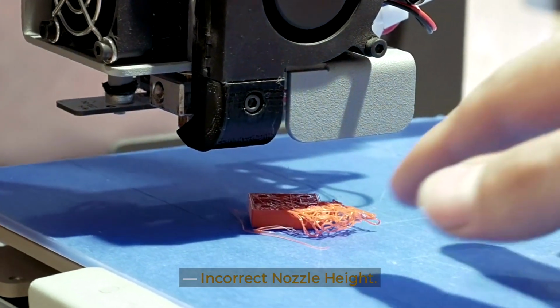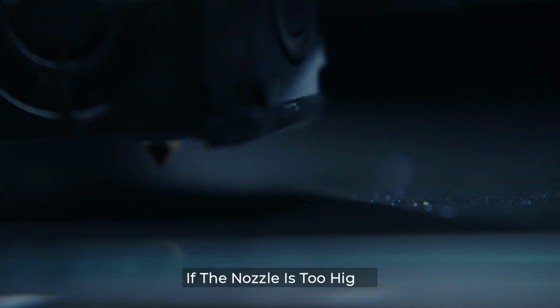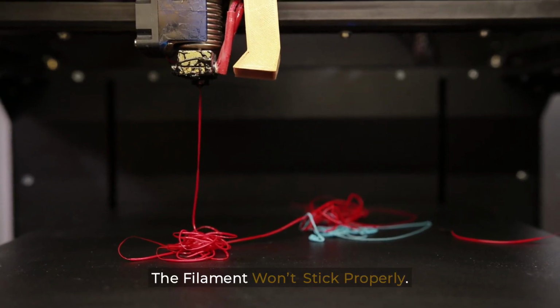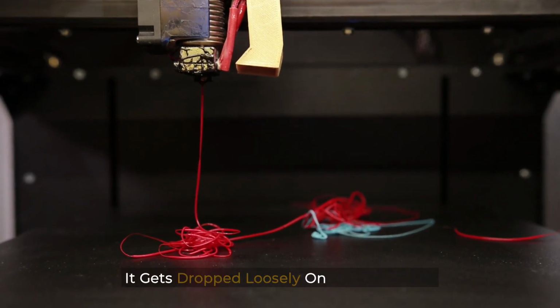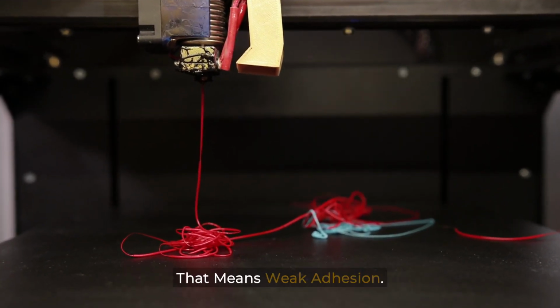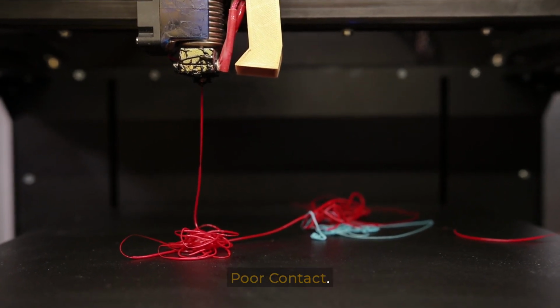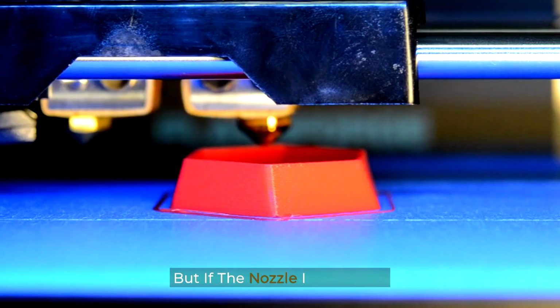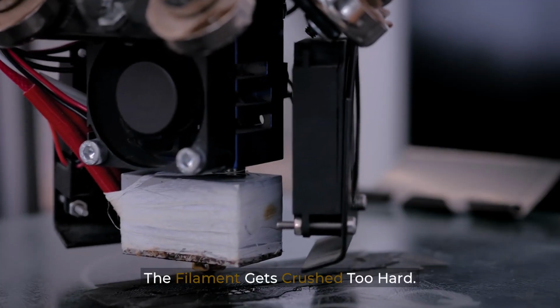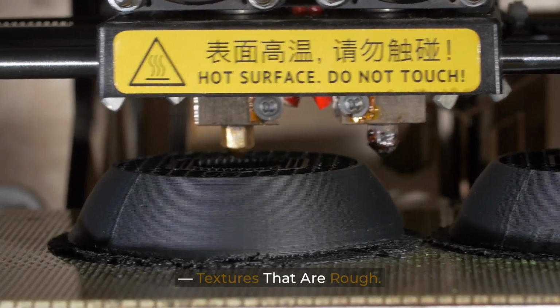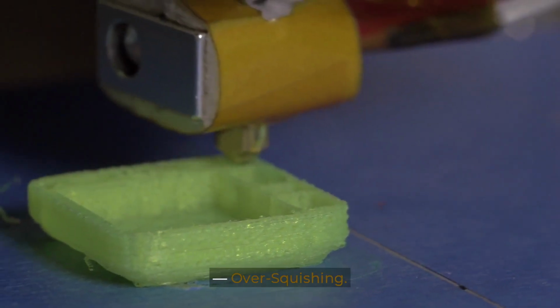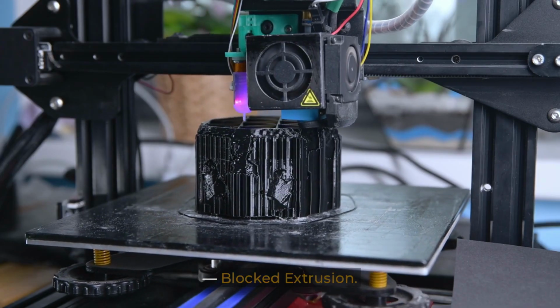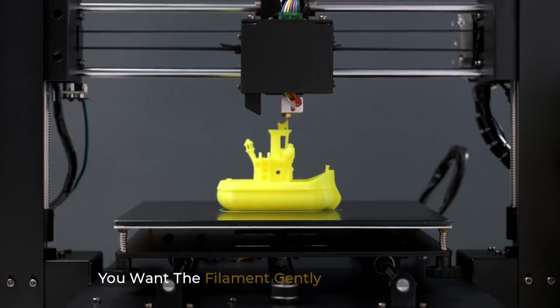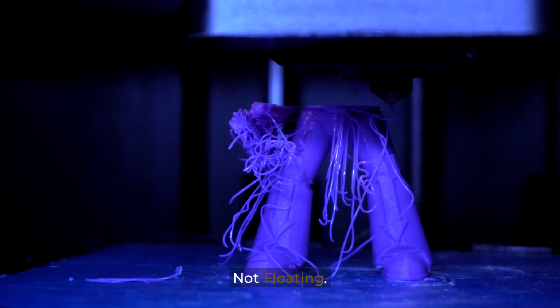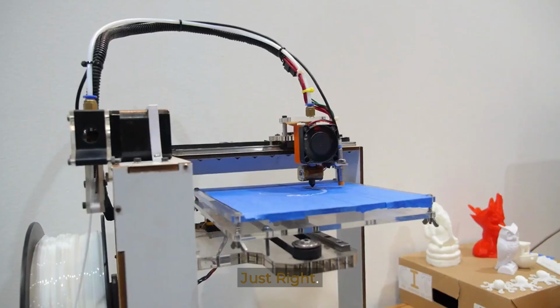Incorrect nozzle height. This is the #1 beginner problem. If the nozzle is too high, the filament won't stick properly. Instead of being pressed onto the bed, it gets dropped loosely onto the surface. That means weak adhesion, poor contact, and eventually, detached prints. But if the nozzle is too low, the filament gets crushed too hard. This can create textures that are rough, over-squishing, elephant's foot, blocked extrusion. Additionally, nozzle scraping. The goal is balance. You want the filament gently compressed onto the surface, not floating, not crushed, just right.